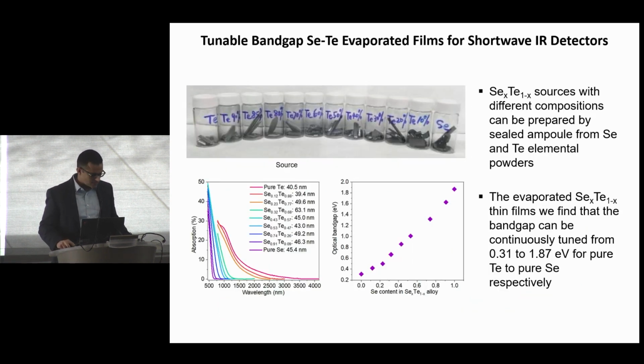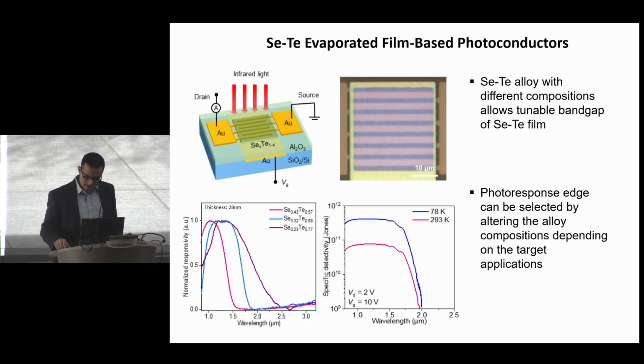Now, tellurium is also a good material for light absorption. In the bulk form, the band gap goes from 0.3 electron volt to about 1.9 electron volt if you alloy it with selenium. And this is the bulk form. If you reduce the thickness, then the quantum confinement effects is dramatic. You get also another degree of control in the band gap. And so we have started to use the tellurium devices as our photodetector technology that we can readily fabricate on chip.